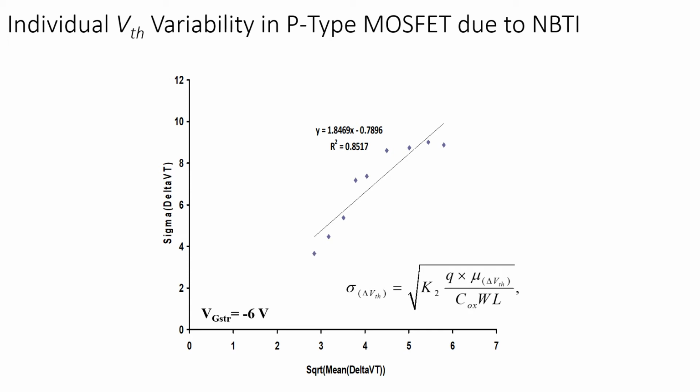So as you can see clearly here, the variance is basically proportional to the mean of this process, and that is what is true also for a Poisson distribution. So from this graph, you can see that NBTI itself is a Poissonian process.